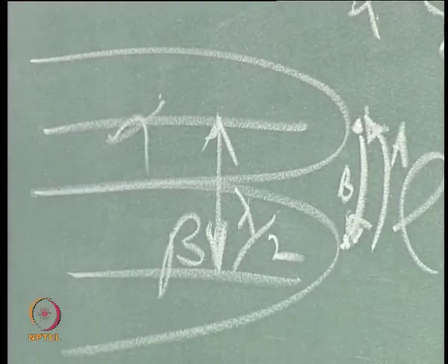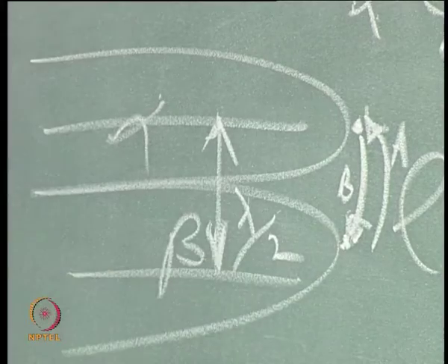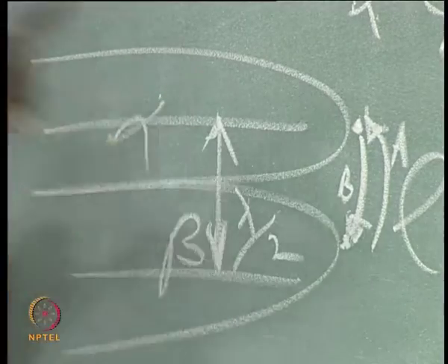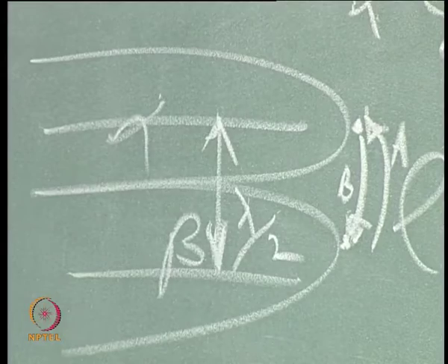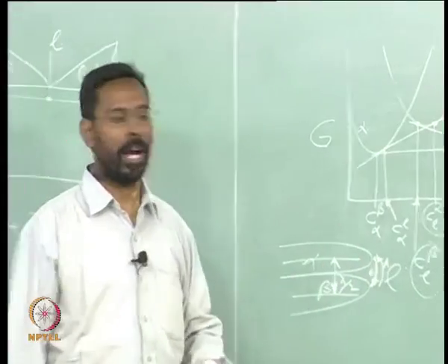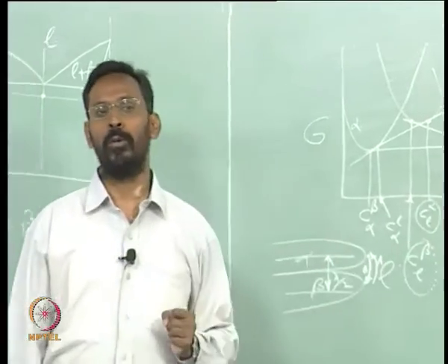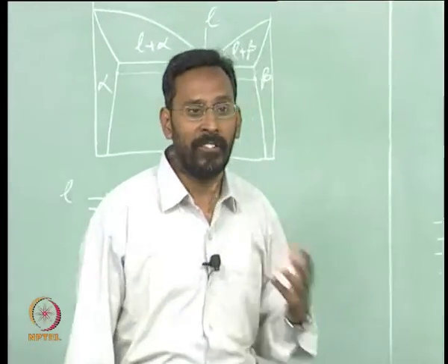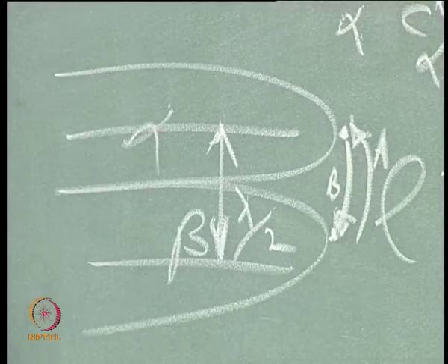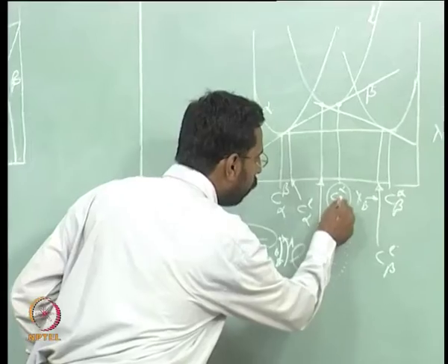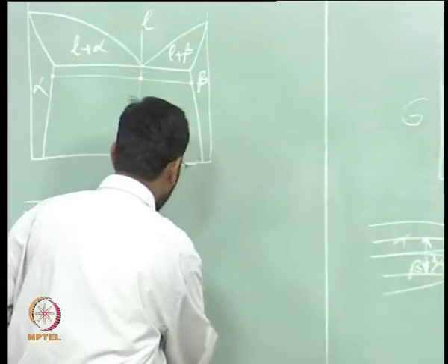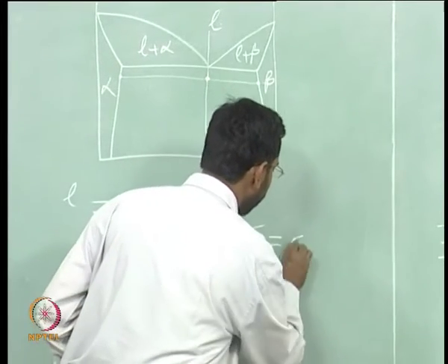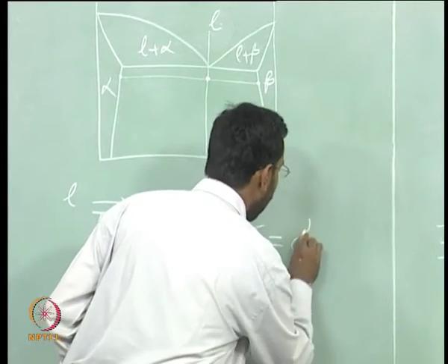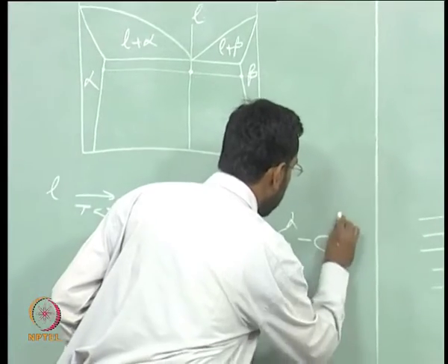This movement of atoms, B atoms going towards the beta and the A atoms going towards the alpha, will make sure that the alpha gets more A atoms and the beta gets more B atoms, so that both of them grow together. And this is driven by what? It is driven by the difference between the composition of this and this, which is what we call delta C, which is nothing but C liquid alpha minus C liquid beta.